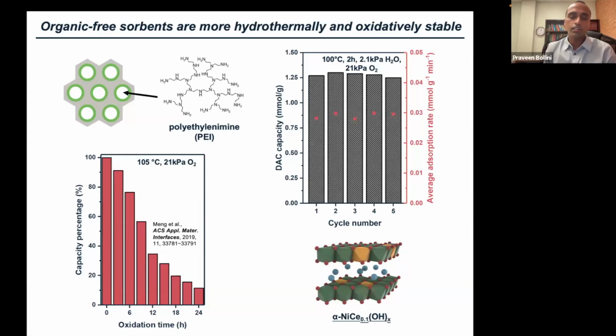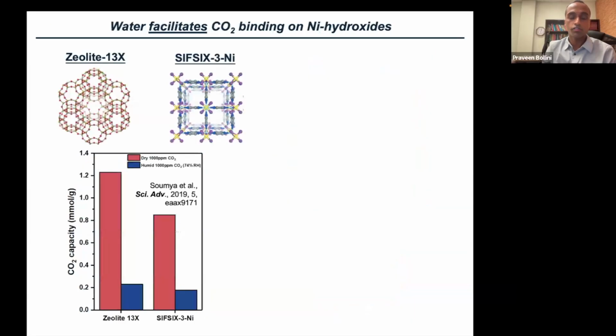So these are relatively aggressive conditions that any organic amines would generally fall apart under, but the sorbents platform is quite robust and remains stable to steam and oxygen specifically. The other really interesting property of these very simple materials is that unlike most materials in which water in fact competitively binds with CO2 and makes the material not viable, water in fact helps or facilitates binding on these materials, which is a very useful characteristic to have.